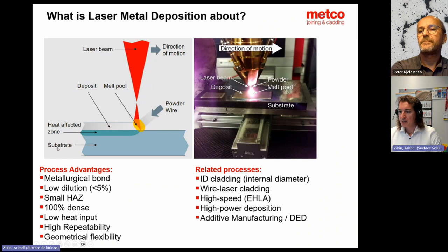However, if we compare laser to classical MIG, MAG, and even PTA processes, the core advantage is dilution. I don't know, Peter, if you know what dilution is. Yeah, it's the mix between the substrate and the powder you add. So typically in welding, you have like 50%. It's typically a 50-50 mix.